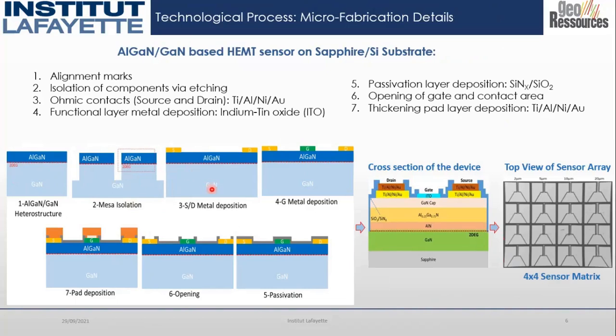Then we deposit the source and the drain metal, followed by the gate metal, known as the function layer. To stabilize and protect the surface properties of our transistor, we put a passivation layer throughout our device. Then we open specific areas of the passivation, like the source, the drain and the gate, to put our pad metal for thickening the contact. At the very end, this is the end of our fabrication process, and we find a device like this. When we dice our device, each die comes with a 4x4 matrix of sensors.